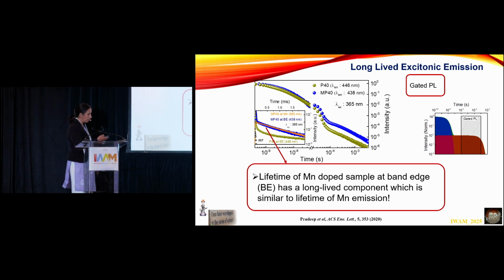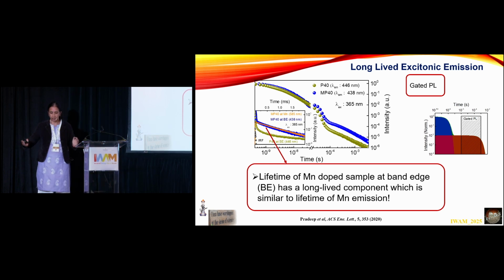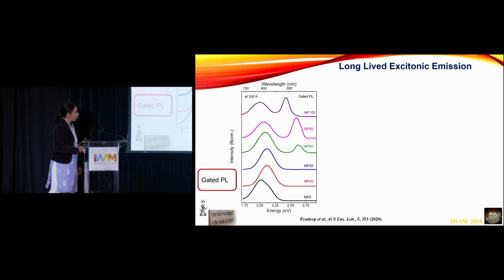When I say gated emission, what I mean is that I'm going to ignore all the fast component, the first few nanoseconds, first few microseconds, and then collect the steady state emission across the entire spectrum. This is known as gated emission because I'm going to insert a gate and then collect the rest of it. When I did a gated emission, we found something very interesting. When people have earlier done gated emission, they expected the manganese emission almost very similar to this, because manganese is millisecond long-lived, and I expect after a few microseconds manganese was there.